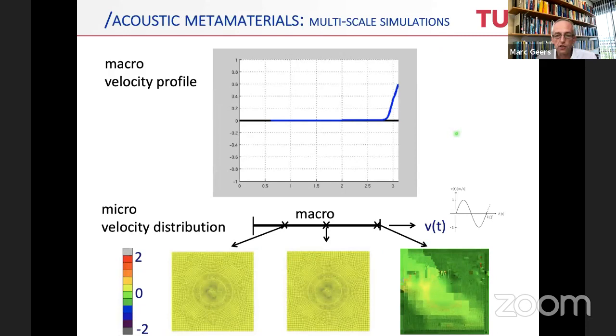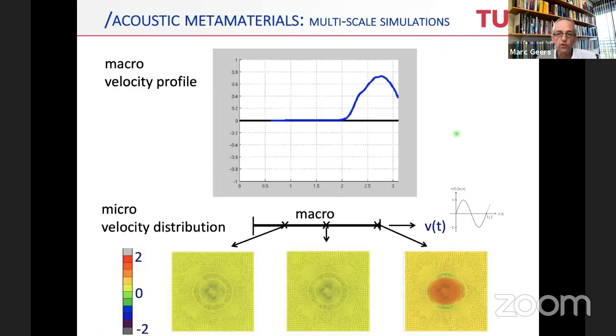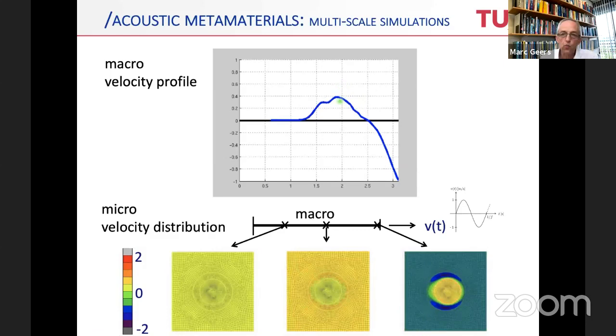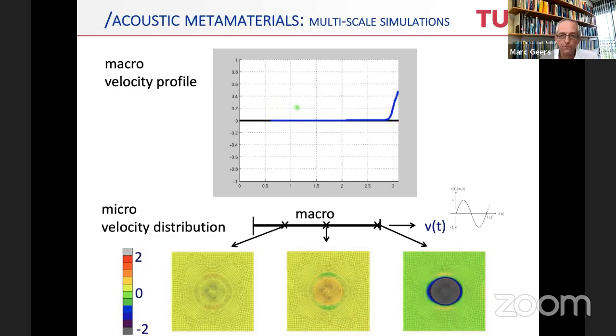This is a typical result. There are some movies at the bottom that could be really slow, also on the top. On the top, you see a wave entering a system at the microscopic scale. The only thing I want you to notice here is how the amplitude is decreasing as the wave is propagating through the structure. That's what the top movie should show. Some of you may see it, maybe some not. At the bottom, you see the vibrational modes. If you could see the movie, you'd see that on the right side, the particle is in this resonance state, vibrating, whereas on the left side, the inclusion is almost in a steady state and not moving anymore.